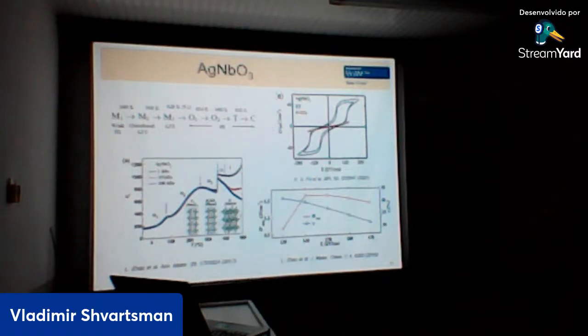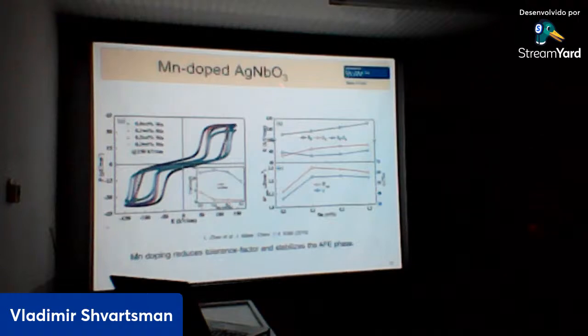Another example of antiferroelectric is silver niobate. Just to show you shortly, it has also at low field almost linear behavior, but when we increase the field, we have a transition into ferroelectric state, which partially goes back to the antiferroelectric, but finally a significant amount of ferroelectric phase remains when we decrease the field. Again, this material is not bad, it's good for energy storage, and when we dope this with manganese, we can reduce this amount of the remaining ferroelectric phase, so we can reduce the remanent polarization, and correspondingly our efficiency will increase from 40% to 55%, and at the same time the stored energy will also increase.